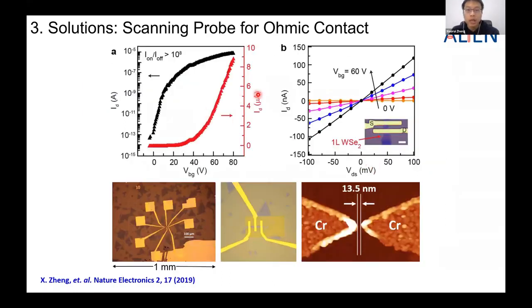Okay, so to demonstrate the versatility of our method, we also fabricate some transistors on tungsten diselenide. This material is very famous. It's very challenging to make good contacts. However, we still can achieve very good n-type conductivity in one layer tungsten diselenide, and the on-off ratio is up to 10 to the 8. And we also observe linear IV dependence on this monolayer transistor. It's a good indication that our method is universal to other 2D materials, not only MoS2.